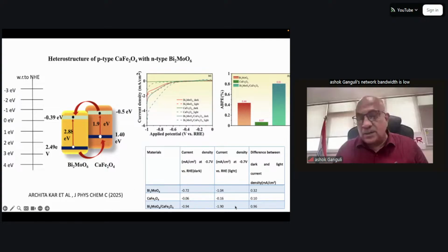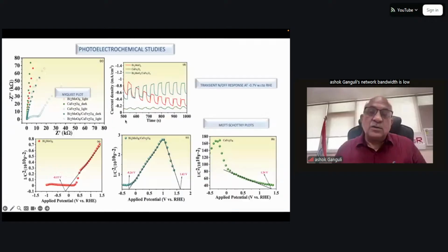Now you can see the measurement of the current density, right? And that is increasing in the heterostructures compared to the bare materials. You can do cycling studies, how many times you can do this on off, which kind of shows that it is a stable material. You can use it for longer time. But of course, for real applications, you have to use it for much longer time and show it is stable.